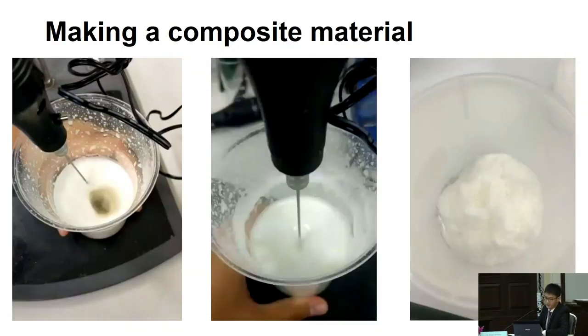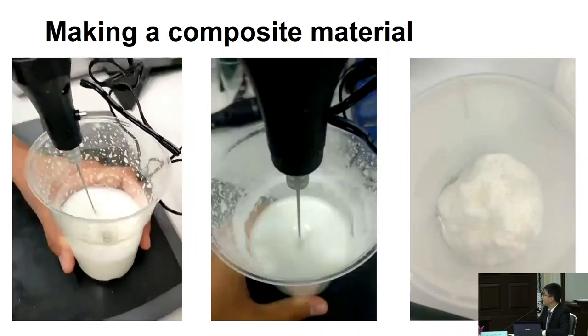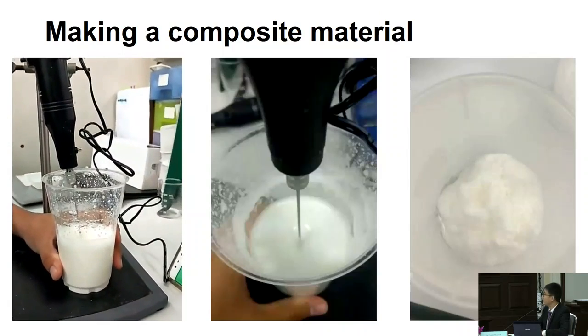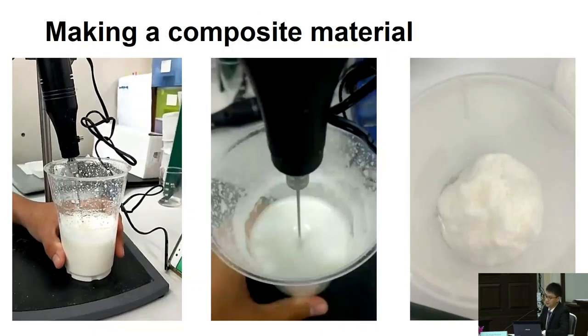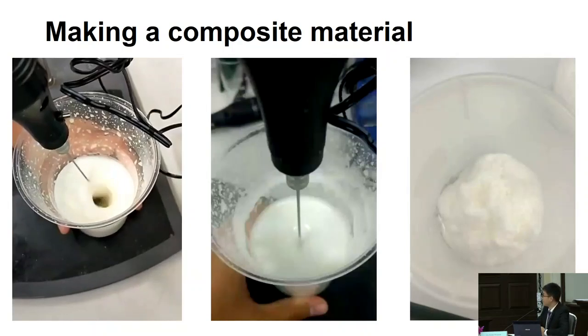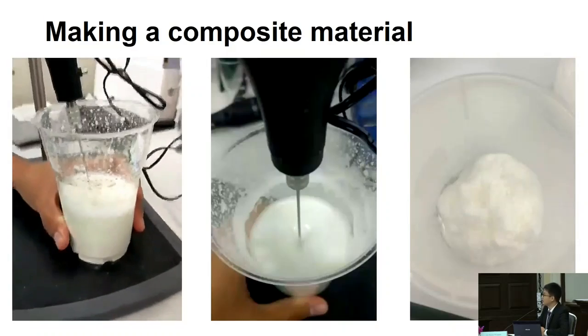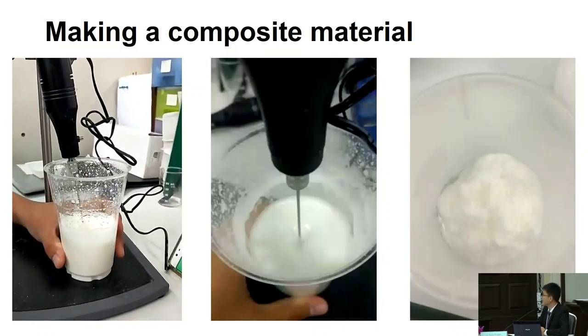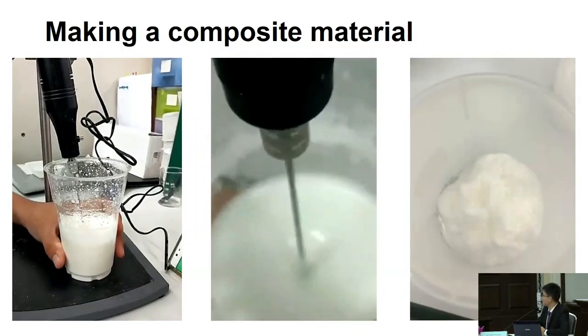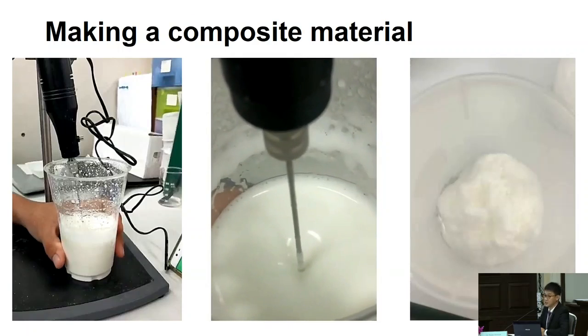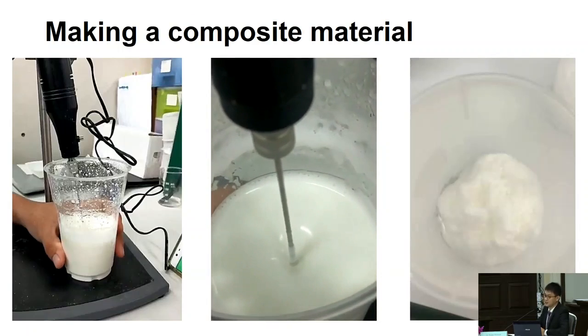And then we mix the two solutions together and we foam it. You can notice the viscosity of the solution. Initially, it is not very viscous. It's very runny. And then after 20 minutes of frothing, the viscosity increases a lot. After that, I put this into the oven, and the foam structure stabilizes itself. And then finally, I got the scaffold.